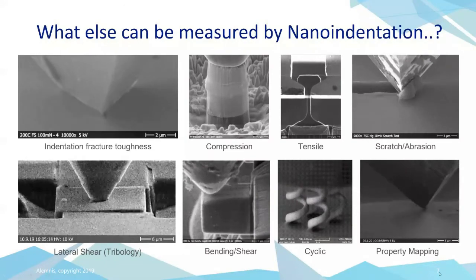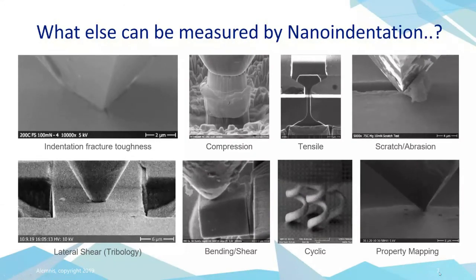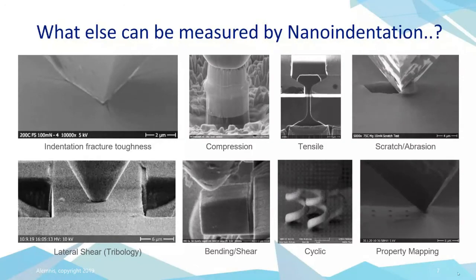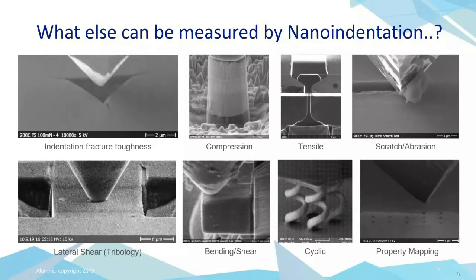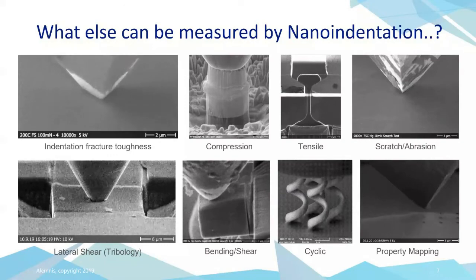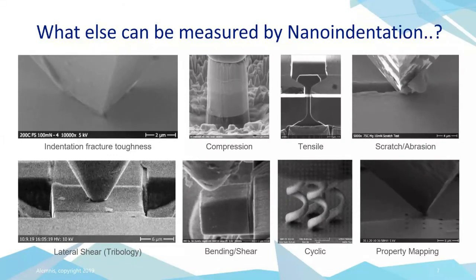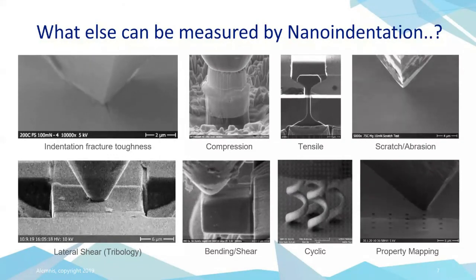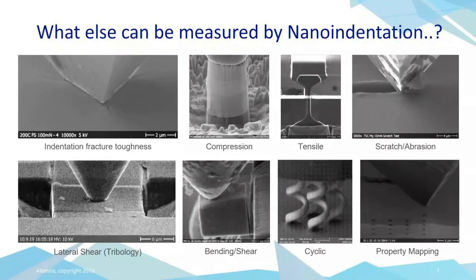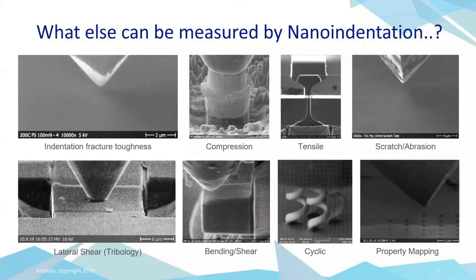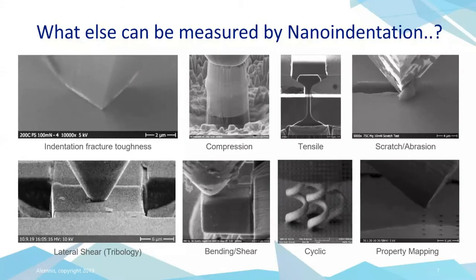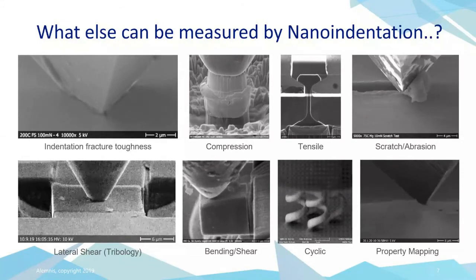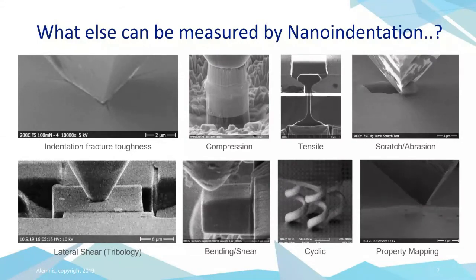Final example here is mapping, and I'll talk a bit about this later on. This is the ability of the nanoindenter to map properties across the surface by making large arrays of indents. So this is an example across an interface, and you can see we're basically doing typically an indent per second. So very, very fast mapping, which then allows us to measure mechanical properties across the surface.